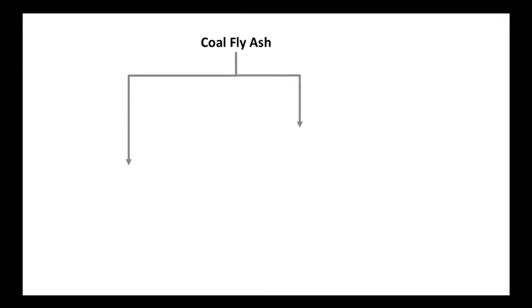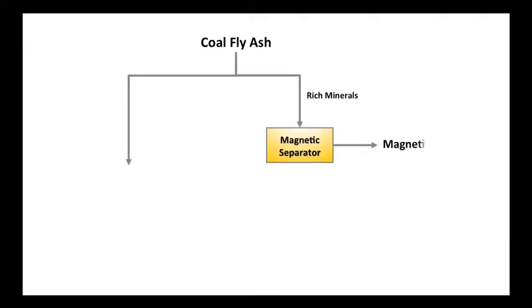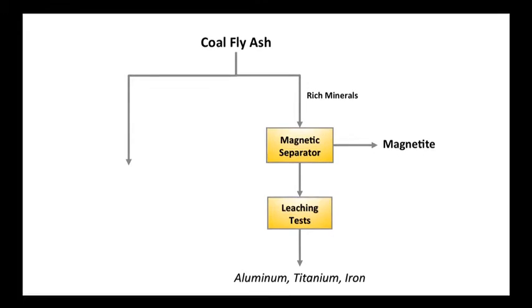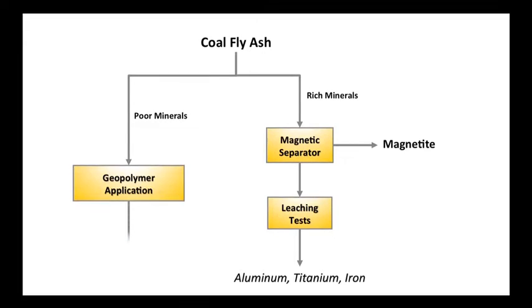If the fly ash is rich in valuable metals, a series of mineral separation applications can be applied to recover them in the form of metal oxides. In our study, about 95% pure magnetite can be recovered from fly ash using a magnetic separator. The non-magnetic fly ash contains a high percentage of aluminum, titanium, and other metals that can be leached out using acid solutions. On the other hand, if the fly ash contains poor minerals, it can be used to generate cementless concretes through geopolymerization processes.